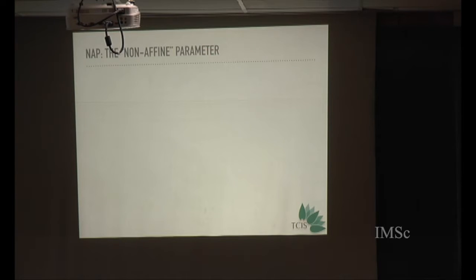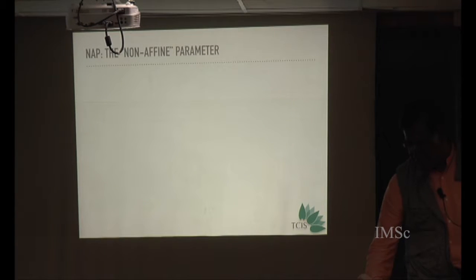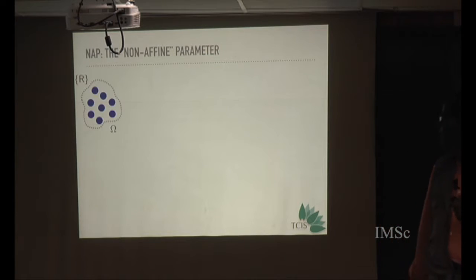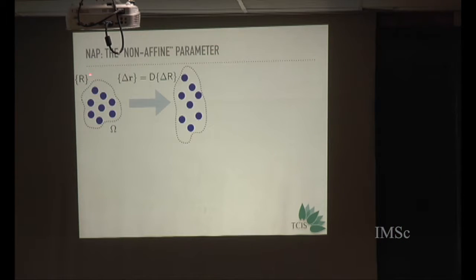Okay, so what is this non-affine parameter? This is something which was introduced in the glass literature, maybe even a decade or slightly more back, and the concept is not very difficult at all. Suppose you have a set of particles and they have a reference configuration. This could be the ideal lattice, it could be inherent structures in a glass, it doesn't matter, and a coarse graining volume which you decide. It could be the interaction volume. So you look at all the particles in this coarse graining volume. If you deform this reference and make it something else by multiplying it by a deformation matrix, then this is an affine deformation. Okay, so you have multiplied everything by a single matrix.